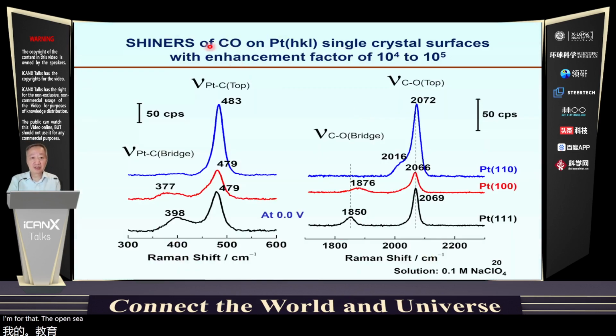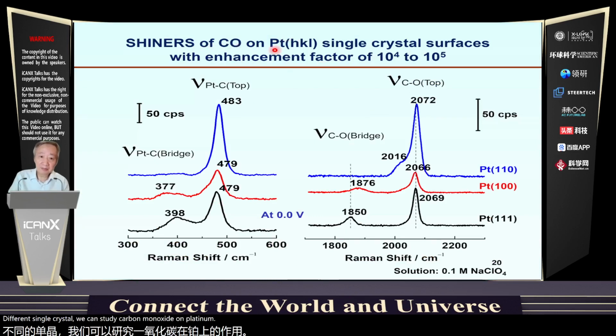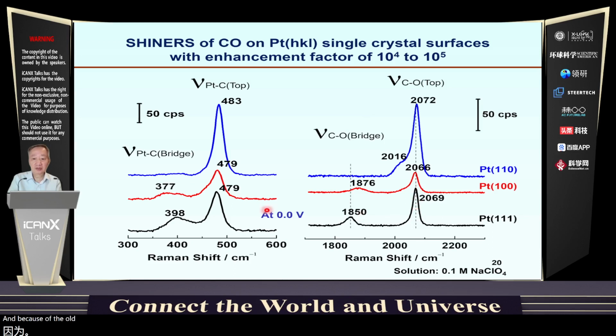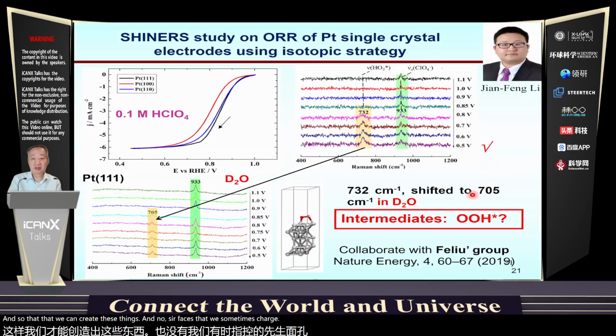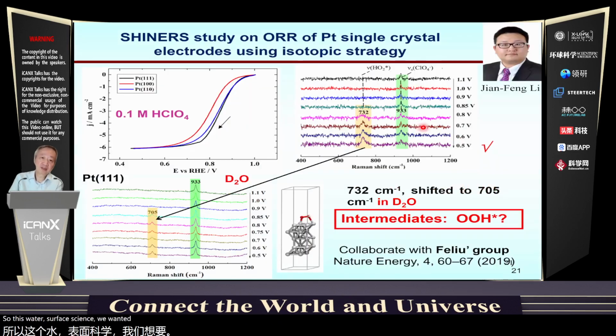As you can see, with SHINERS, we can study different single crystals. We can study carbon monoxide on platinum, which is very important for catalysis or electrochemistry. And we still can get the enhancement factor from 10^4 to 10^5. So as you can see, these are the different single crystal faces, and because CO can adsorb on different sites, on top or bridge, we can clearly distinguish those faces with different structures. So that's what surface science wanted.